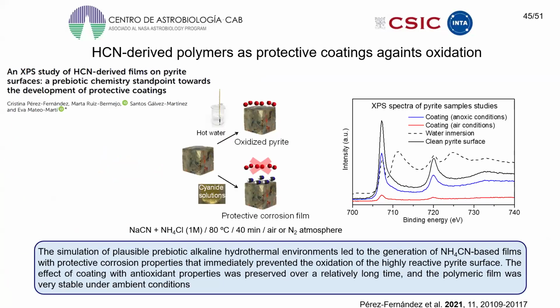On the other hand, we have also observed the great potential of hydrogen cyanide derived coatings as protective materials against oxidation. In this case, we immersed pyrite, iron sulfide, in a hot water solution of cyanides. Surprisingly, no oxidation of the pyrite surface was observed by X-ray photoelectron spectroscopy. The surface was covered quickly by a thin cyanide based film.